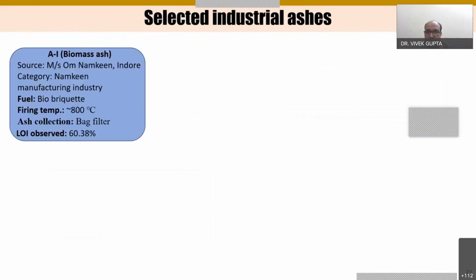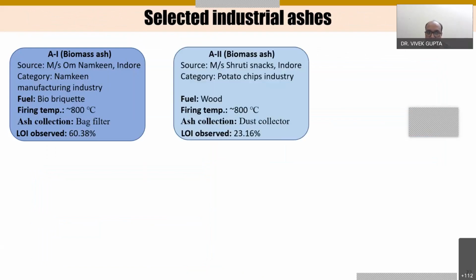We carried out our study on six different industrial ashes. We collected two biomass ashes from local industries, Om Namkeen and Shruti Snacks, which are industries in Indore. In the A1 ash, which is a biomass ash, they are using bio briquettes as fuel, and the firing temperature is 800 degrees Celsius. The ash collection facility is a bag filter, and we observed a high LOI, almost 60%, 60.38%, in the biomass ash A1. Whereas in A2 we observed 23.16% LOI, and the ash collection facility they were using is a dust collector.